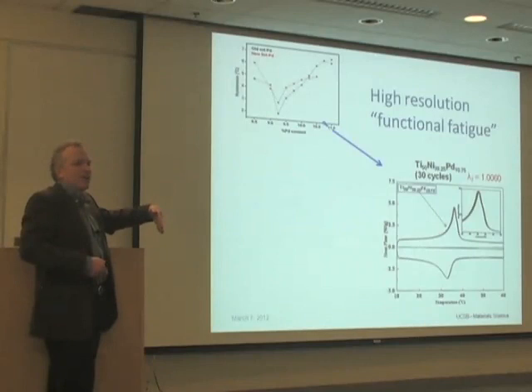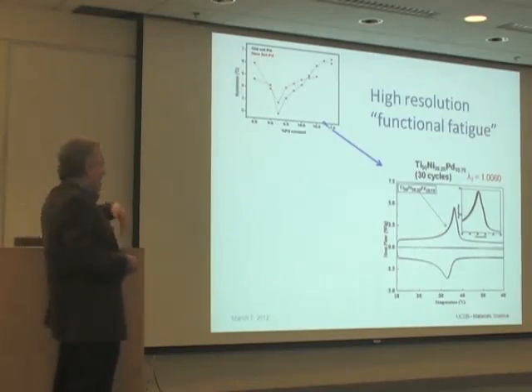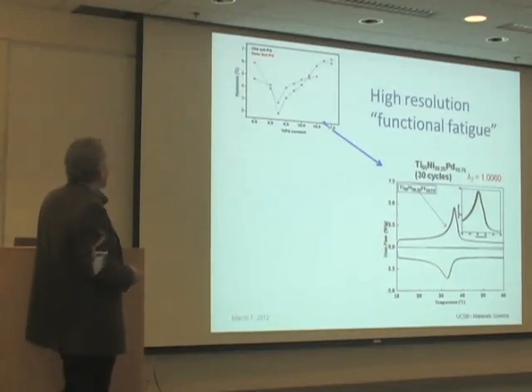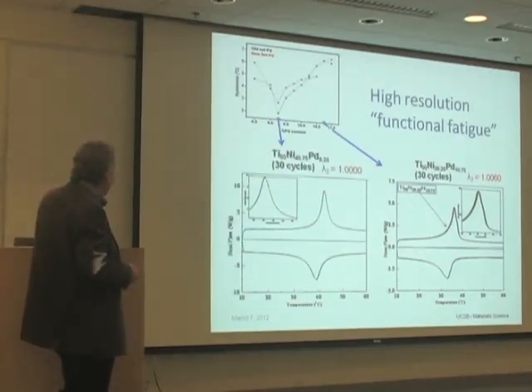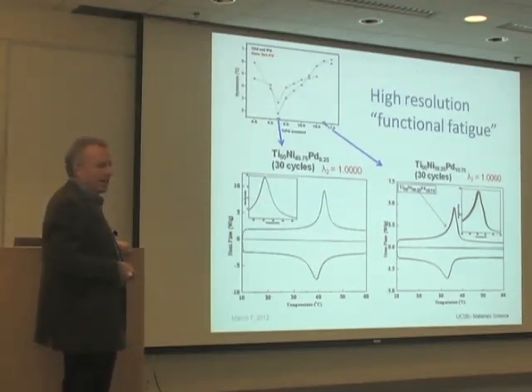So it's interesting to look at what happens to that when you go from this point here to middle eigenvalue equal to 1. And that dramatically changes. So about 2 orders of magnitude change in the migration of the phase transformation temperature with cycle. And we take that to mean that this is a definite improvement in the reversibility of the phase transformation.